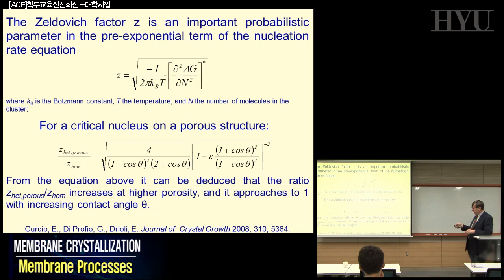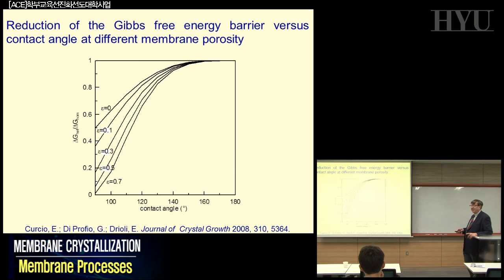Now, if you do this kind of analysis and you go to see theoretically what is coming out, this is the behavior that you expect in terms of Zeldovich factor, which is exactly, at least qualitatively, the kind of performance that you saw before in the experimental results that we are getting in the formation of real crystals of different proteins, etc.